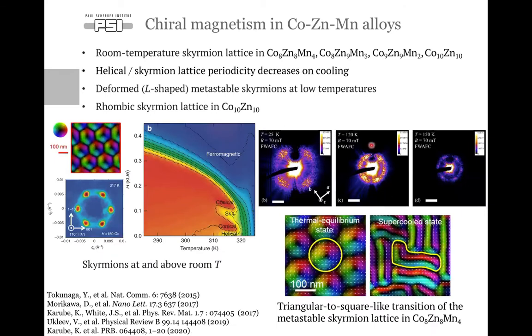The most famous compounds are 8-8-4, 8-9-3, 9-9-2, and 10-10 due to their high ordering temperature and therefore the possibility to get a thermal equilibrium or metastable skyrmion lattice at room temperature or even above. Also, it is interesting that in cobalt zinc manganese materials, the helical and skyrmion lattice periodicities can be changed with varying temperature. Thus in 8-8-4, for example, that has an ordering temperature around room temperature,